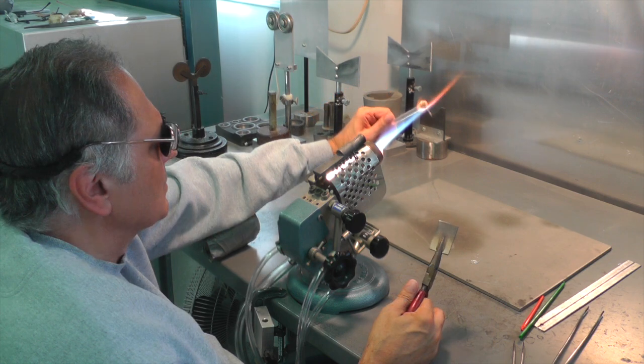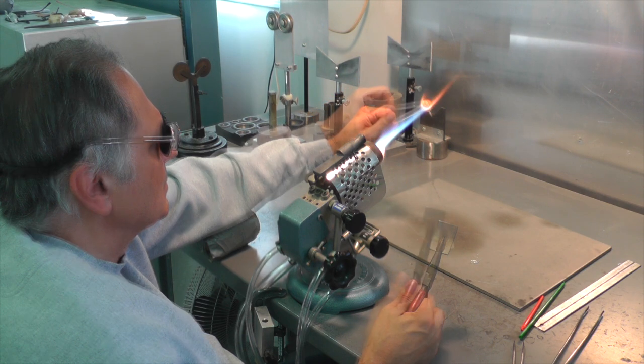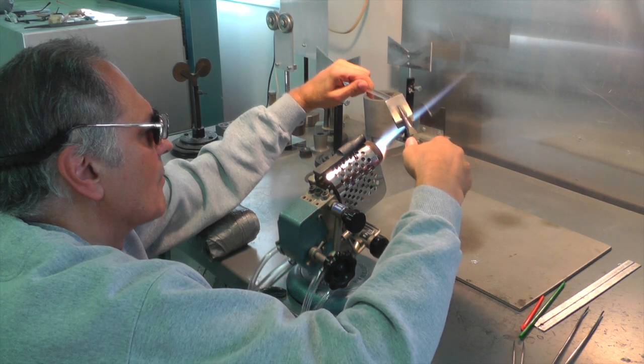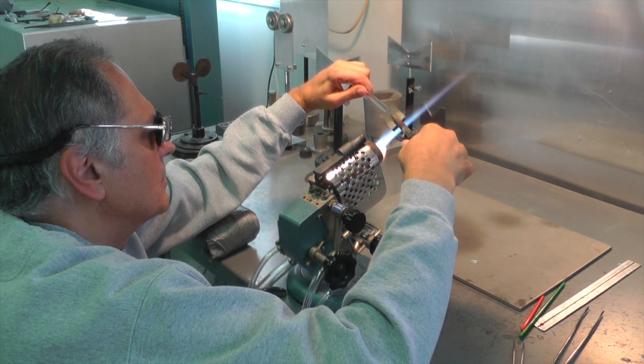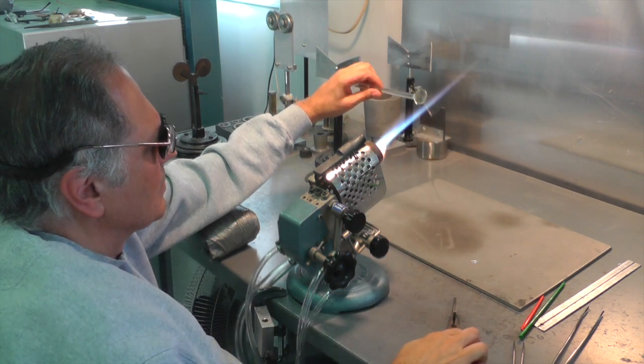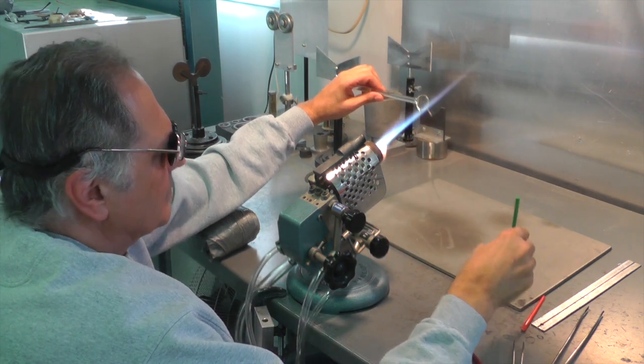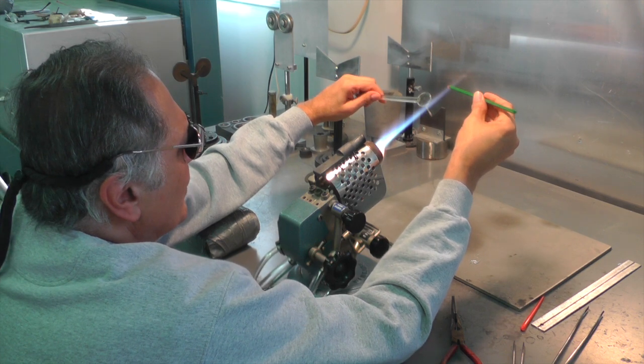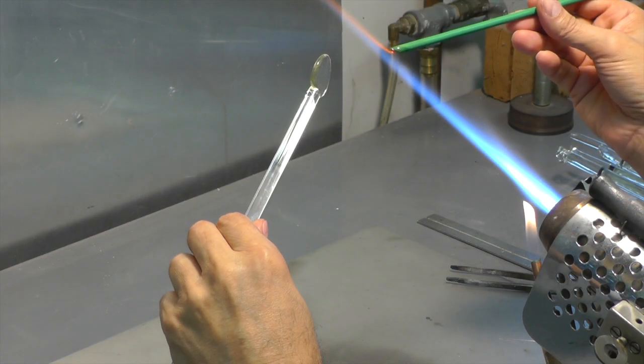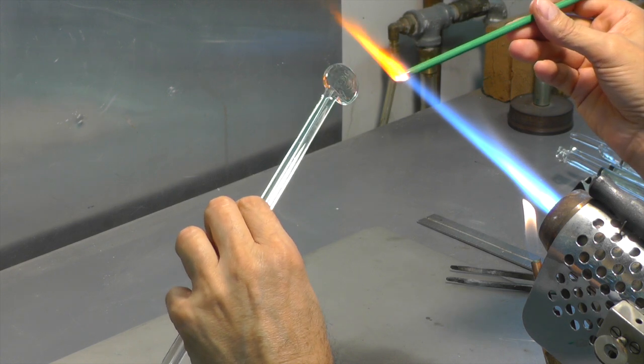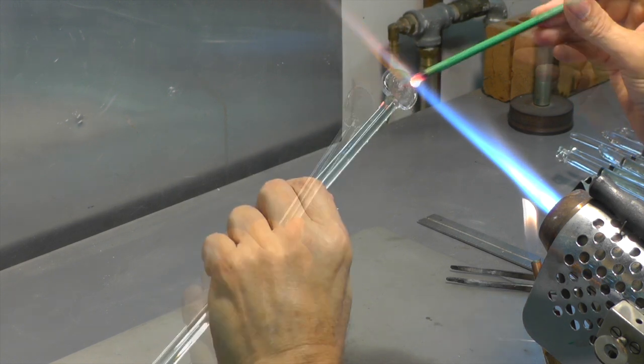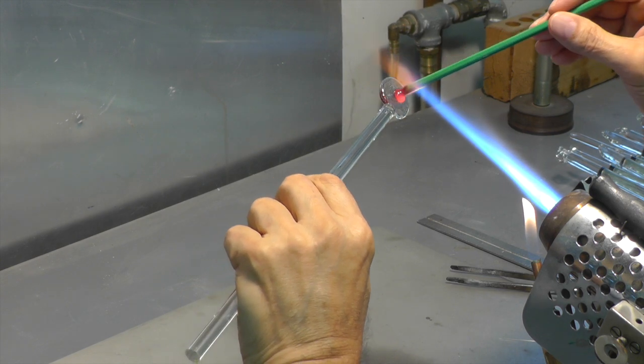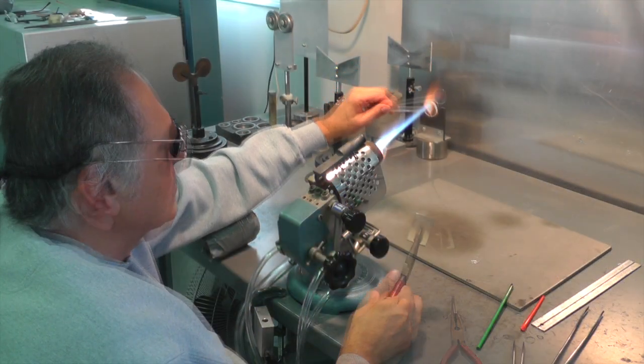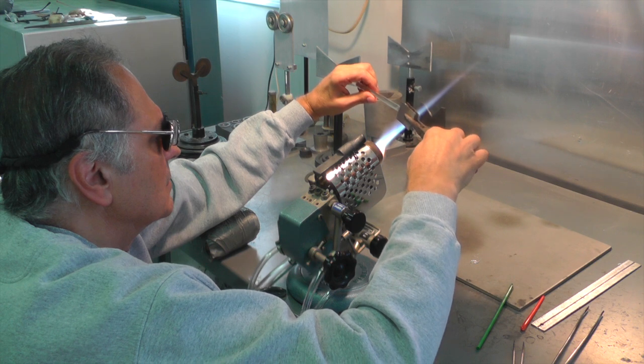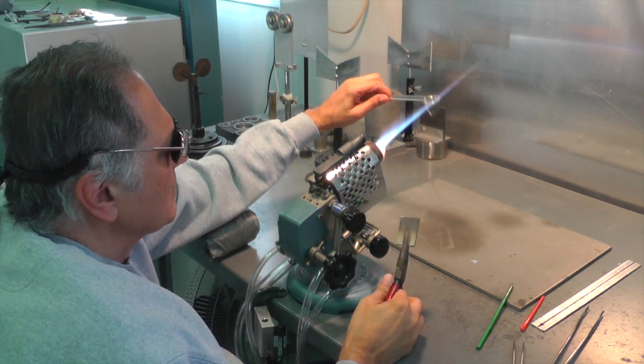This is how you would make a sample in the torch to test out a color to see if they're compatible. Here I'm just heating up a small section of 104 clear and flattening it out. Then I'm going to use some 104 green. I know these already match, but I'm just going to show you what they look like in the Polariscope. So we heat up a section and put out a small amount on top. Then you heat it from the back and get it really soft so that you can push the color right into the crystal.